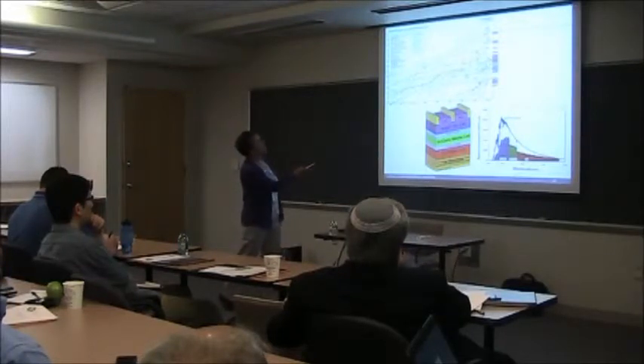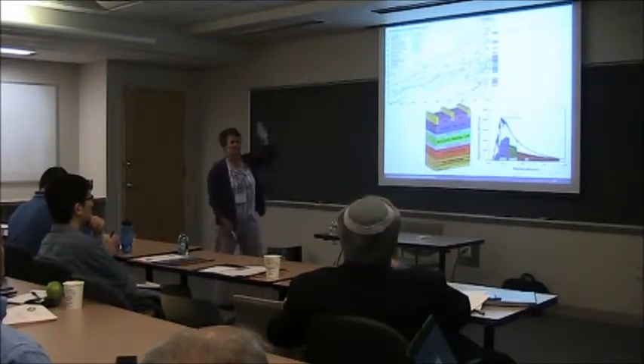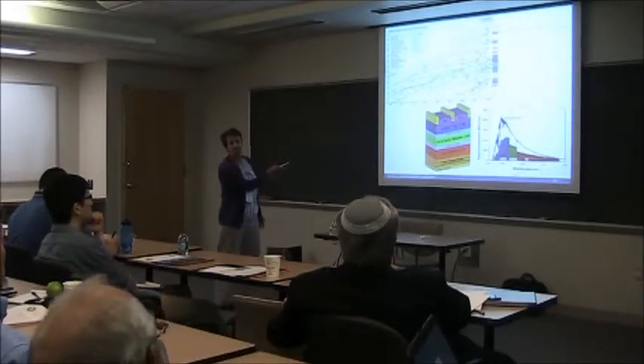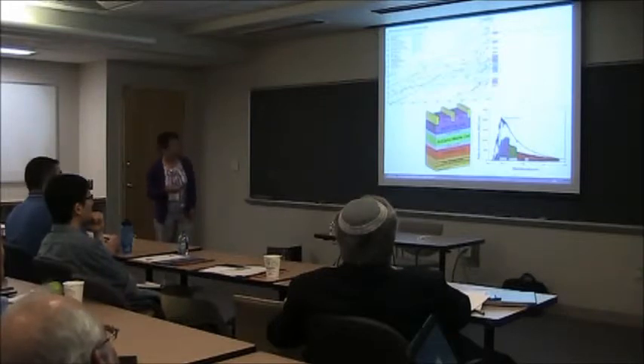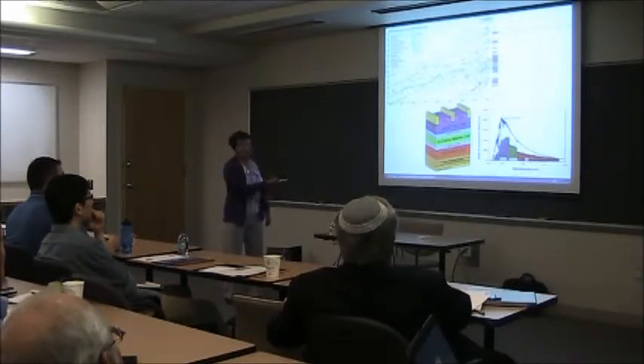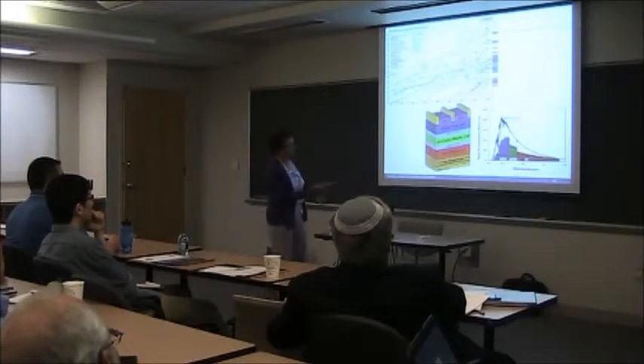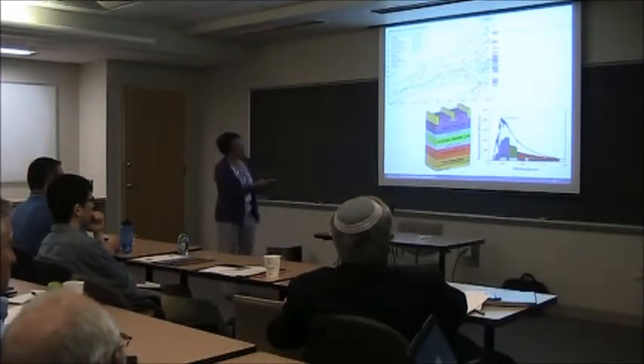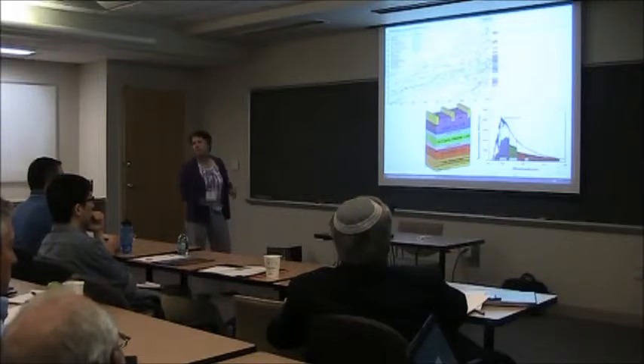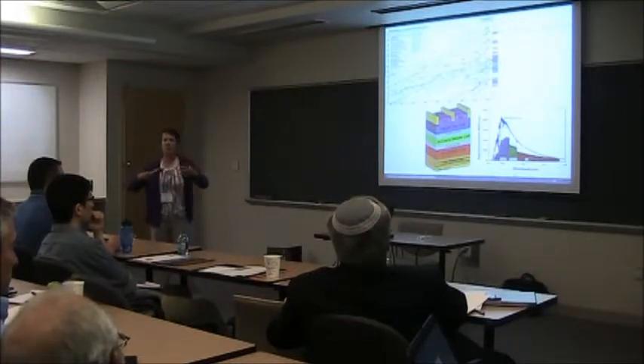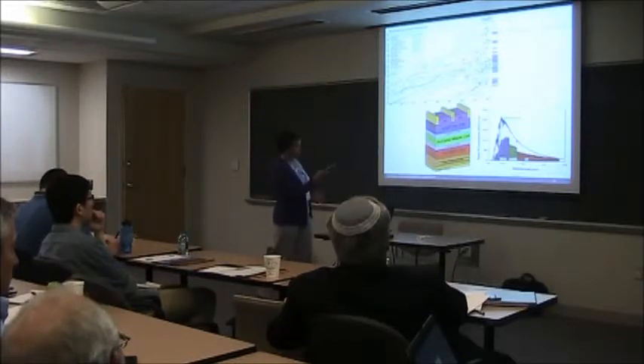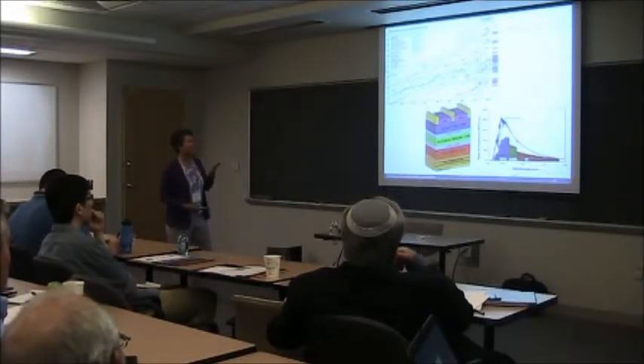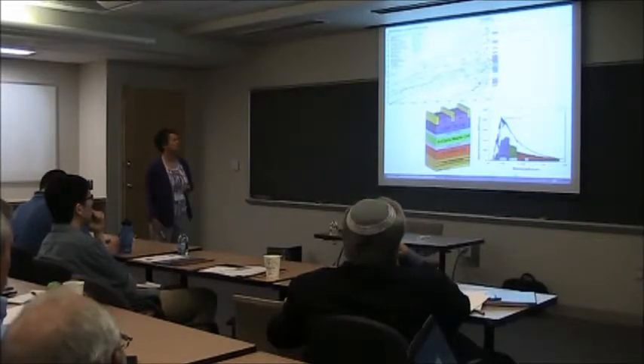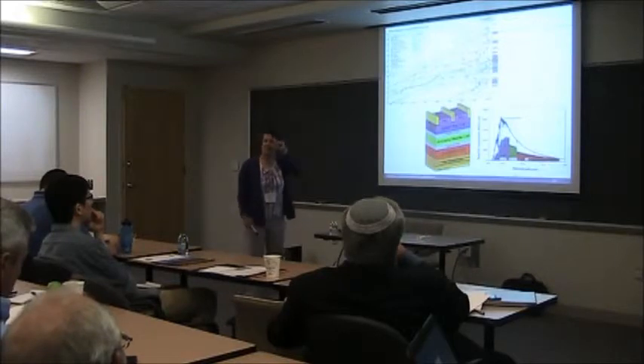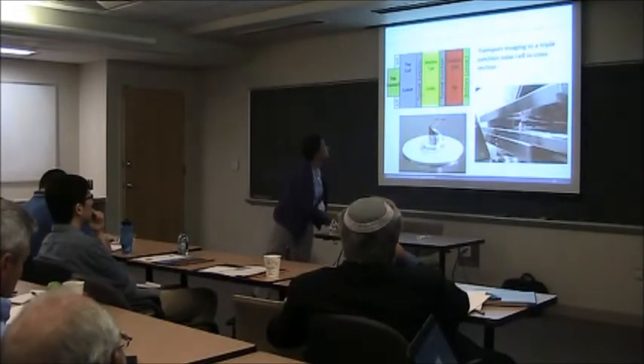Here's the perovskites, if you're paying any attention to that story. Perovskites are making a lot of these people very nervous. So we're watching that. That's a very interesting story. But anyway, let's talk for a few minutes about triple junction solar cells. The idea, of course, is you're going to grab different parts of the spectrum. One of the things I want to do is think about doing transport imaging now in a structure like this in cross-section, to really watch the motion of energy within this. They're 45% efficient now. I think the theoretical limit is about 60-something, depending on the structure. But in the solar cell business, every percent matters. So if you could capture where some of that other energy goes when you lose it, that would be good.